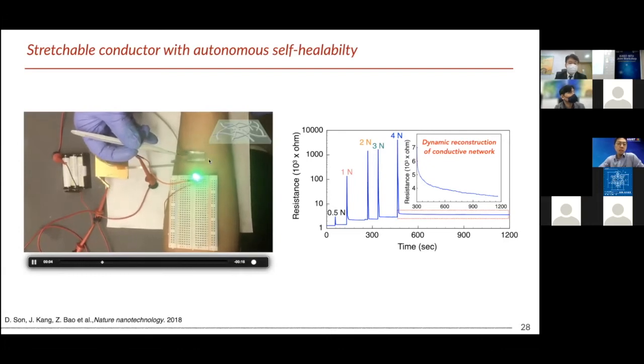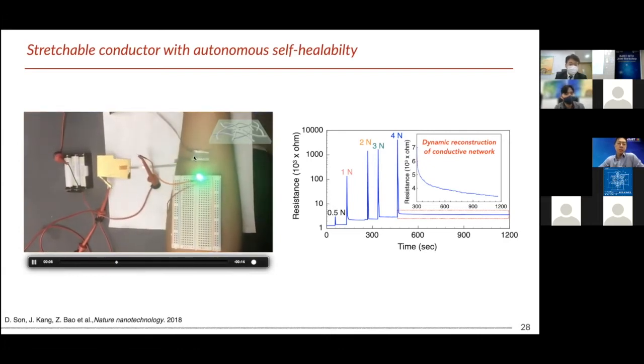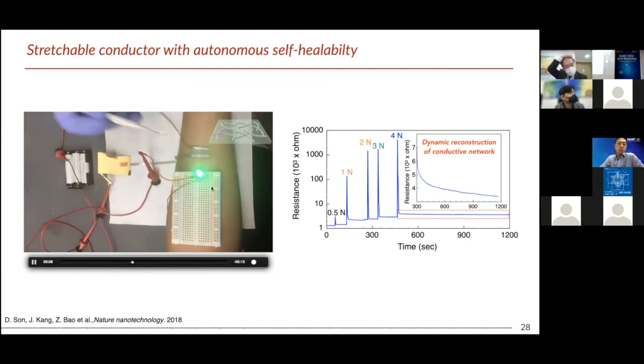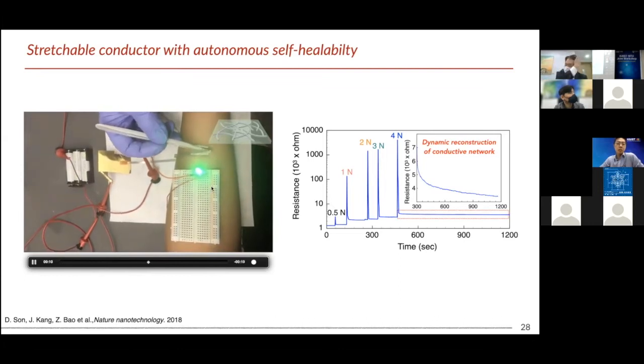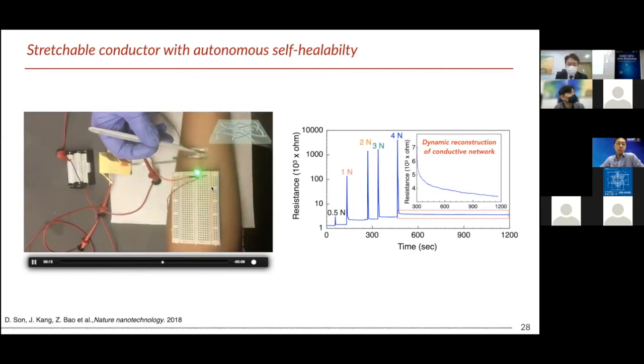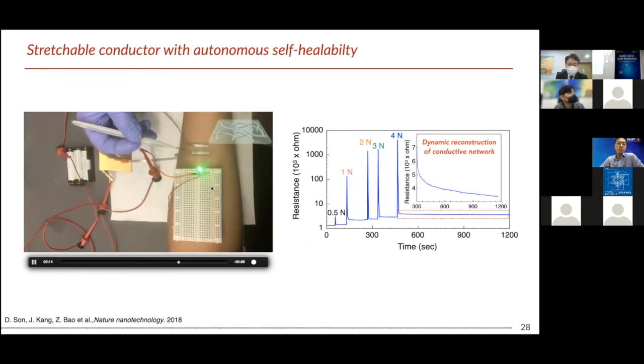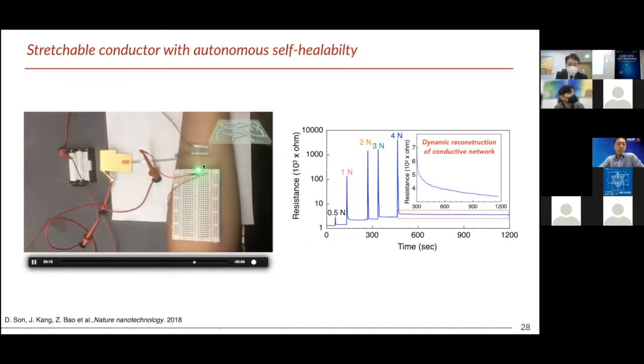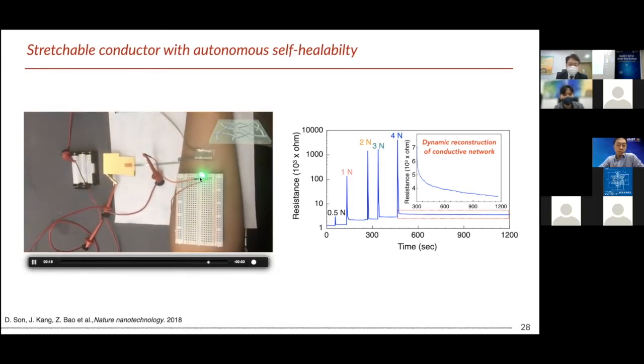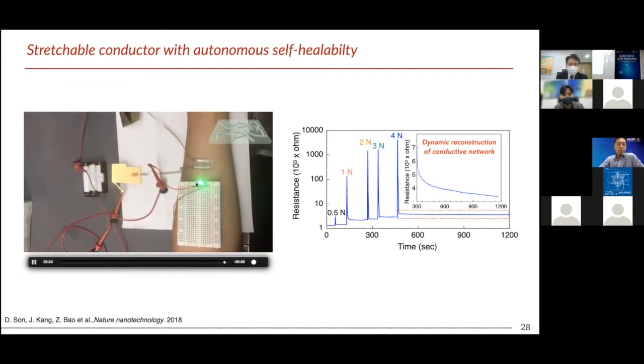So initially, if you scratch with a very low power, you can see there's no change of light intensity. So we start to increase the power of the scratch to fully damage the surface. In this case, at this moment, it's very unstable, but they start to restore their bright intensity, meaning that they can reconstruct their network and restore the electrical properties.